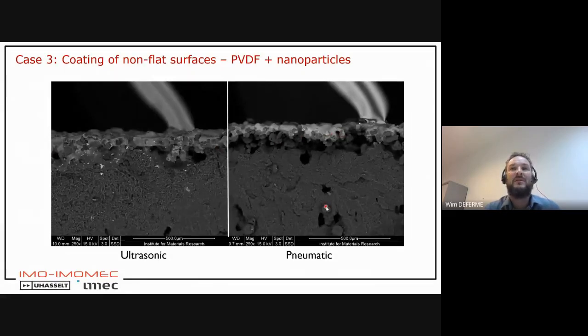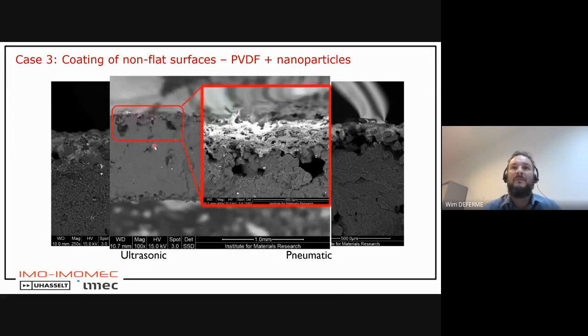So that's an advantage, because you do not alter the dimension of your 3D printed part, but also improve the adhesion, because if the PVDF absorbs a bit inside the SLS printed PA12 part, then also the adhesion of the coating on top or inside the 3D printed part is better sticking. So that's also a beneficial thing. Here you can see an optimized graph, scanning electron microscopy of the ultrasonic spray coated layer. So that concludes my talk.